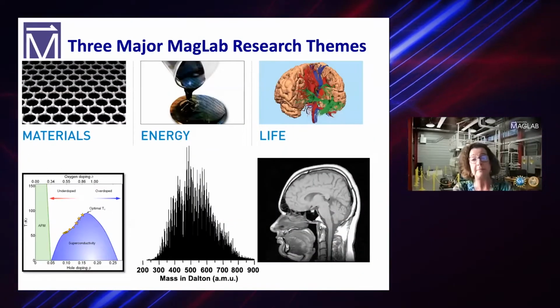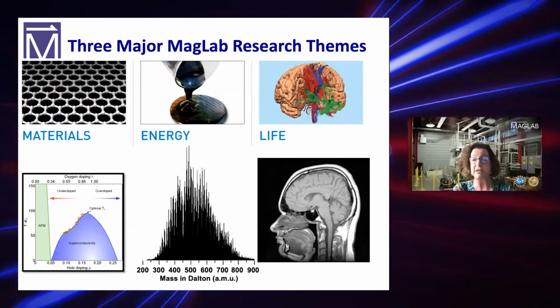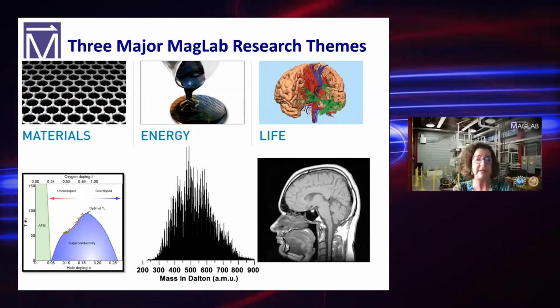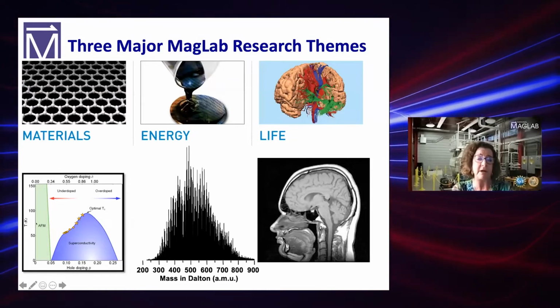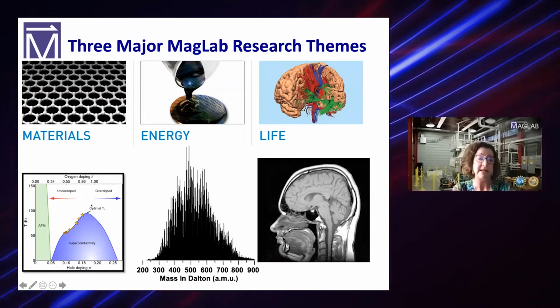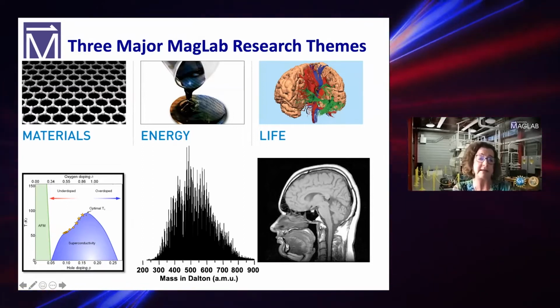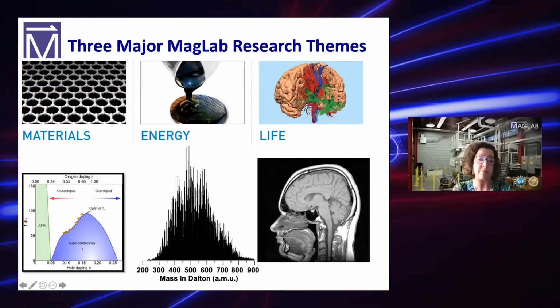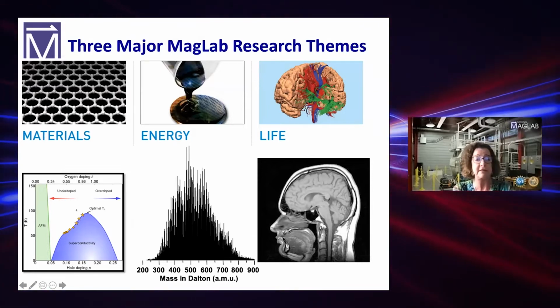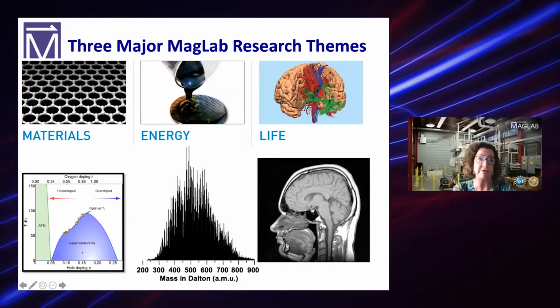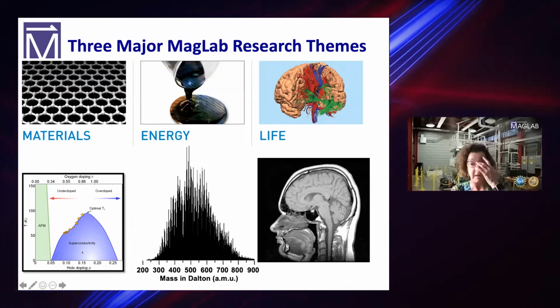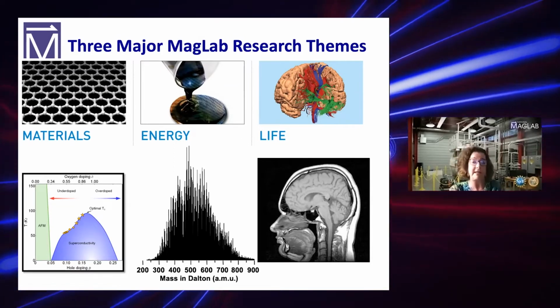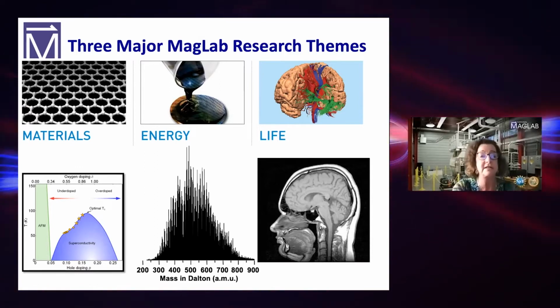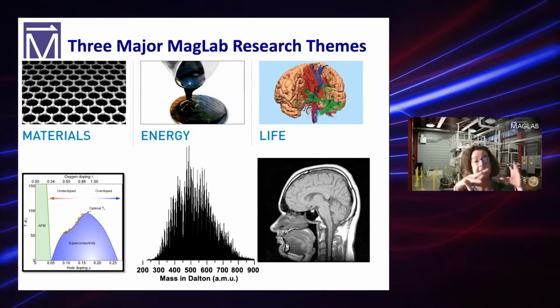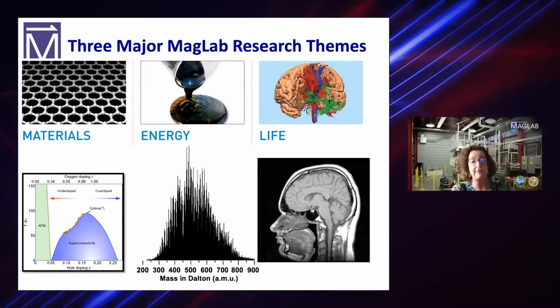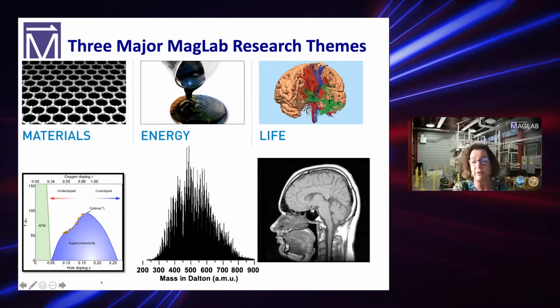The major themes of the Magnet Lab are materials, energy, and life. Now I'll just give a few quick examples here. Here's an example that's a little bit older now, so I won't go into it, but it's the high temperature cuprate and how you can put in high fields and break the superconductivity in the superconducting dome. And one of the measurements from a few years ago showed that there are probably 2 quantum phase transitions under there, because using quantum oscillations, we can show that the mass on the Fermi surface actually starts diverging as you go into the superconducting dome.